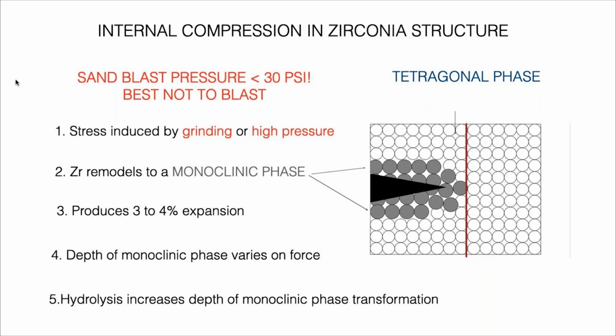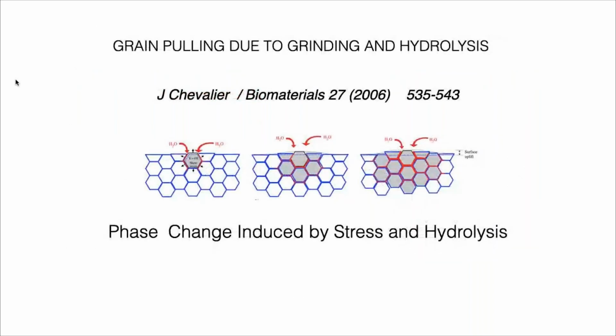And then what happens is, if you keep on, it's called grain pulling due to grinding and hydrolysis. This is a study by Jerome Chevalier from 2006. And a lot of people don't believe this, but it happened in hip implants in a company in Switzerland. I can't remember which one, but they make hip femoral heads. And 1 year in 2003, a lot of them started breaking inside the people. And then Chevalier studied the surface of a lot of these removed femoral heads and saw the abrasion, and they noticed this grain pulling, so that if you have too much stress, these grains grow out, and then the water comes in and it's absorbed, and that starts to weaken the zirconia.